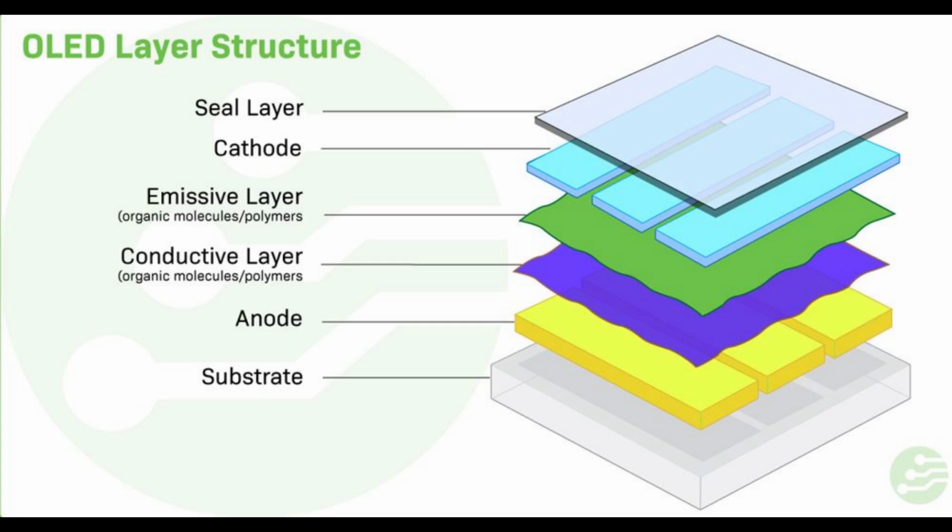However, polymers can be processed in solution, and spin coating is a common method of depositing thin polymer films. This method is more suited to forming large area films than thermal evaporation. No vacuum is required, and the emissive materials can also be applied on the substrate by a technique derived from commercial inkjet printing. However, as the application of subsequent layers tends to dissolve those already present, formation of multilayer structures is difficult with these methods. The metal cathode may still need to be deposited by thermal evaporation in vacuum. An alternative method to vacuum deposition is to deposit a Langmuir-Blodgett film.